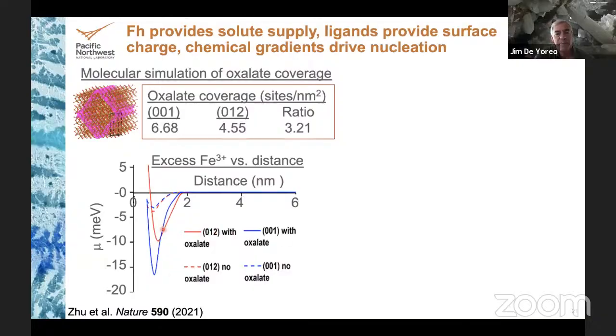So we know the chemistry is different. Now, I don't want to imply that the chemical potential of iron 3+ in the bulk solution is different from the interfacial region. That should not be the case. It ought to equilibrate itself. But the chemical potential relative to hematite is different. And that can result in two things.